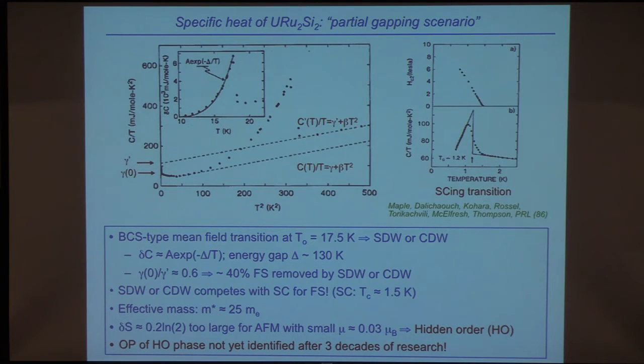Okay, and this is from our own work. Here I've plotted C over T versus T squared, and you see this pronounced anomaly at 17.5 Kelvin, and it's a BCS type mean field transition, it looks like. Again, we thought this was a spin or charge density wave, and you can take this exponential part and infer an energy gap of about 130 Kelvin from it. And also you'll notice that if I extrapolate C over T versus T squared from high temperatures, that will give me a gamma value that I would expect if it didn't exhibit this magnetic order.